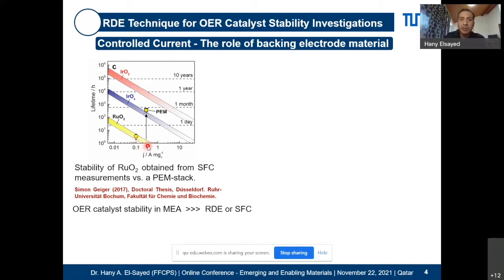oxide is not tested in a rotating disk electrode, but rather in PEM electrolysis, so in an MEA, membrane electrode assembly configuration. What you see is that the stability is much higher. It's about hundreds of hours. So with respect to 2, 3, 4 hours, now we're talking about tens of hours, maybe 30, 40, 50, 60 hours. So there must be some big difference between the two.